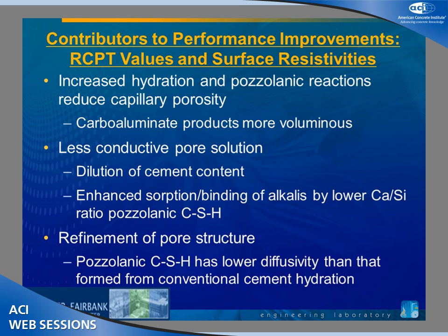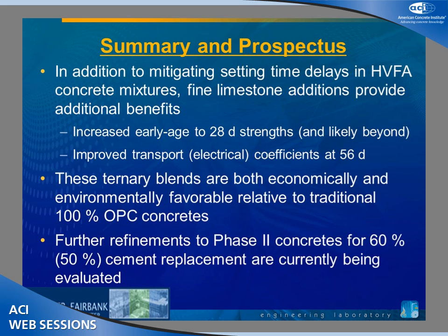You're also diluting the conductivity of the pore solution because you have less alkalis going in, or you have alkalis being absorbed by the pozzolanic products that are formed with the fly ash. And it's well known that the fly ash tends to further refine the pore structure and give you lower diffusion coefficients. So overall, we found that we could indeed mitigate the setting time delays, just like we saw in our pastes and mortars, in the concretes.